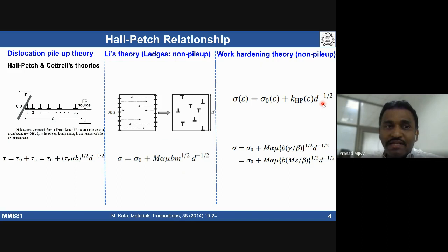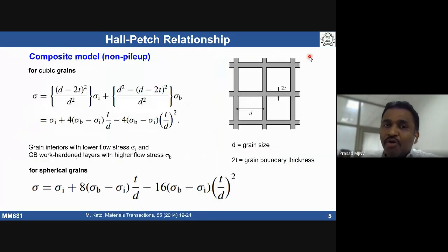There are actually three pile-up theories: Hall theory, Petch theory together as Hall-Petch theories, and Cottrell theory, a common category of pile-up theory. Ledge theory, which is basically called Li's theory, work hardening theory, and the composite model come under the category of theories based on non-pile-up. Dislocations will not pile up, but grain boundaries are going to affect the deformation behavior of a material. The stress depends on d to the power of minus 1/2, inversely proportional to the square root of d. These equations have been derived mathematically by using some assumptions. By using some assumptions, people have arrived at how the Hall-Petch relationship can be derived.